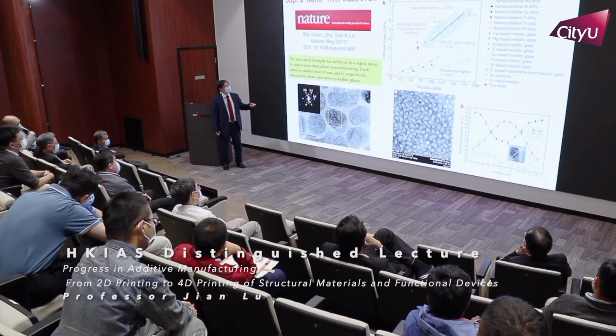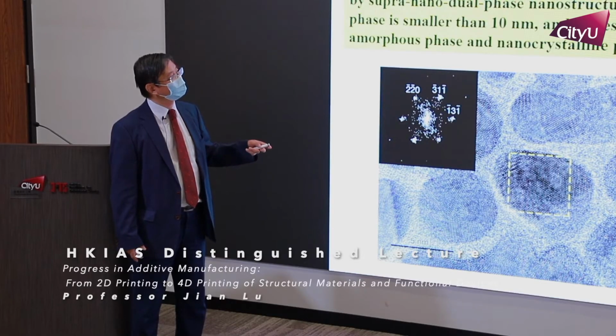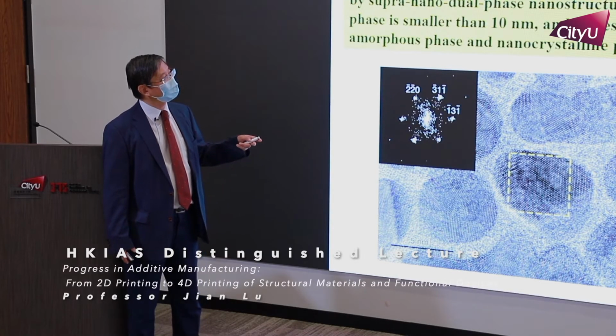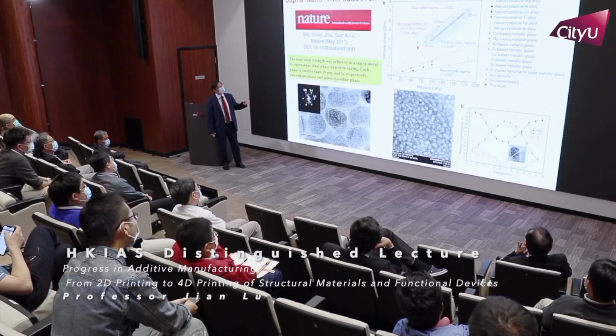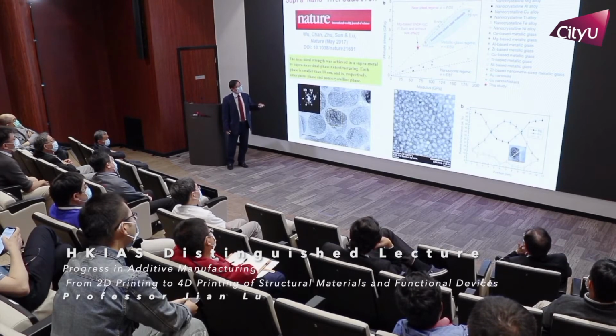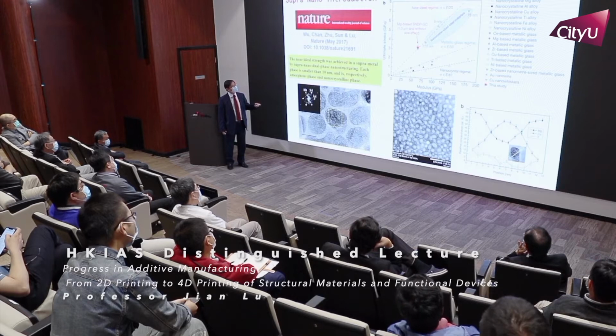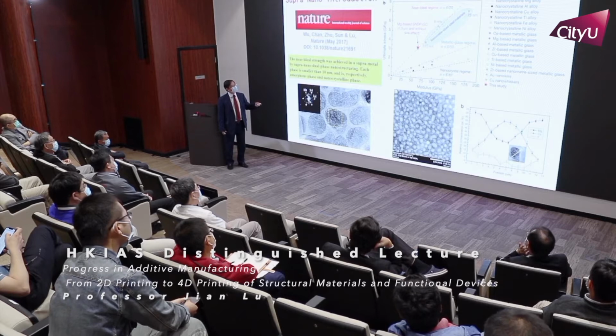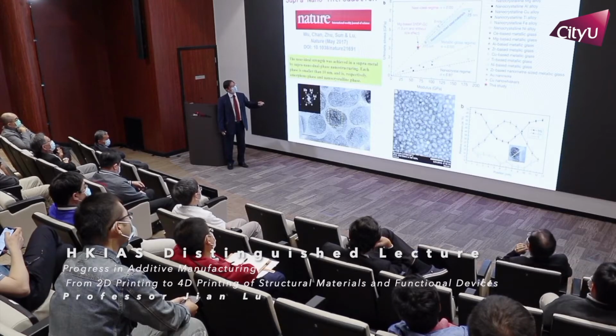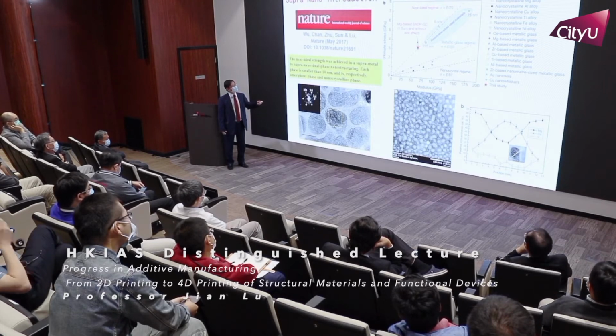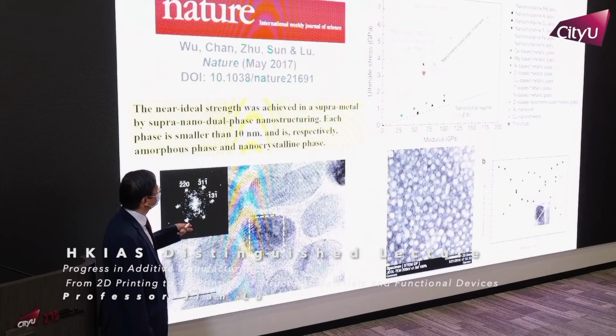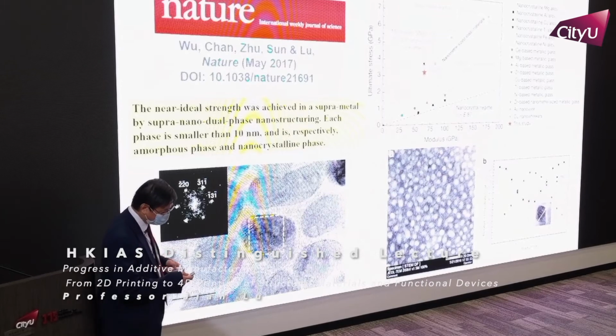Then compared to the theoretical limit of the material, which is Young's modulus divided by 20, you can see the newly created material is very close to the theoretical limit. And before our study, you can see the largest samples close to the theoretical limit were 8 nano, 75 nano, and 220 nano. And here it's still small, but it's 1.3 micrometers.